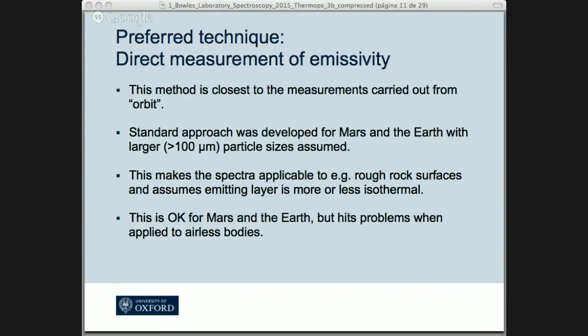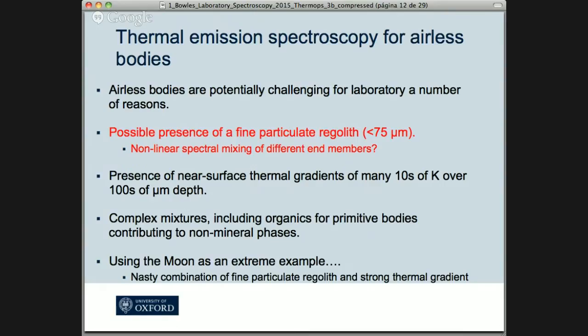What we find for airless bodies is that they're potentially challenging in the lab for a number of reasons. First of all, you have the presence of fine particulate regolith, such as on the moon. This is a really big deal. I've heard the moon referred to as a perfect storm for thermal IR because you've got very complicated thermal structure, with thermal gradients all over the place. This can give you interesting non-linear spectral mixing effects for different mineral end members when you put them into your spectral libraries and try to unmix the resulting spectra.